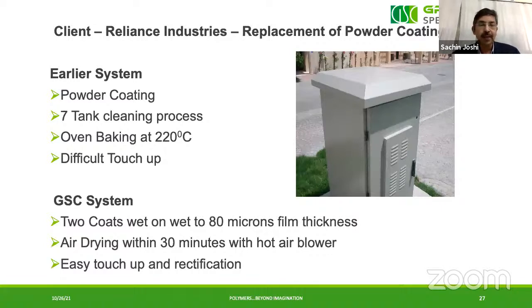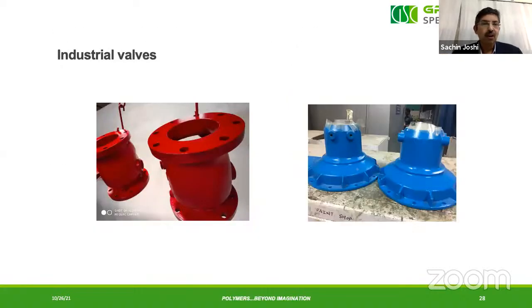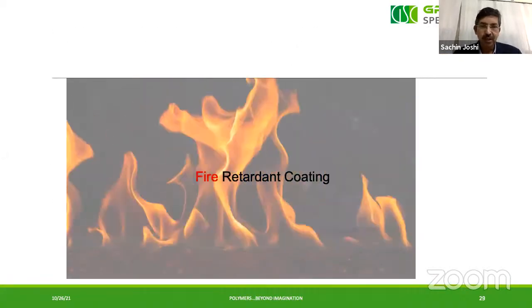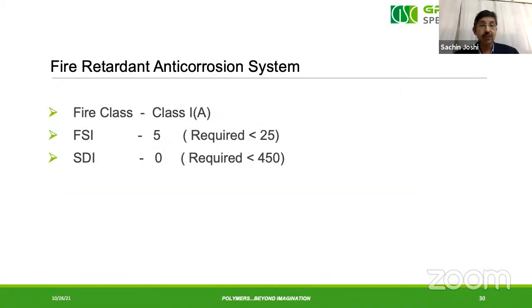We are replacing powder coating. This we have done with Reliance in Jamnagar and Nagothane plant. Entire control panel has been coated with this. There's no 7-tank process, there is no oven, there is no electrostatic gun, simple compressor, just 30 minutes drying, 80 micron thickness and done. Walls we have done, and then we have got a fire retardant coating. It will have a very high fire resistance. So FSI, fire spread index is 5, where people say it should be less than 25. Smoke development is 0. When you take the fire on the coated panel, there will not be any smoke, 0 smoke. So it is fire class 1A.